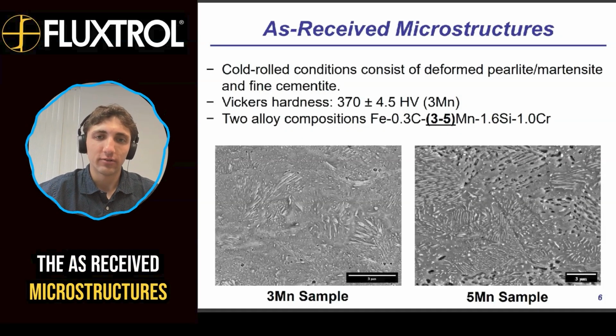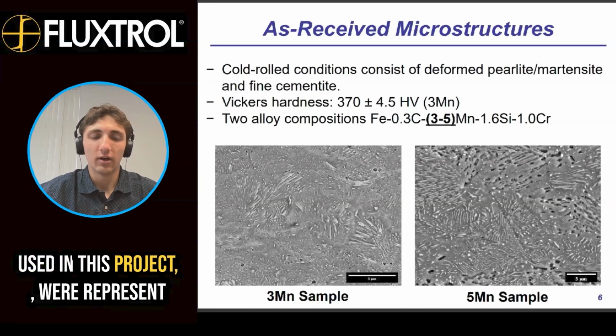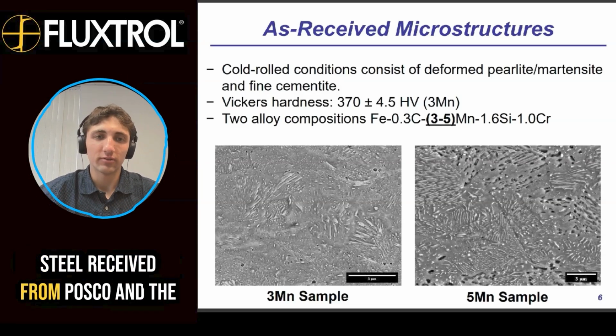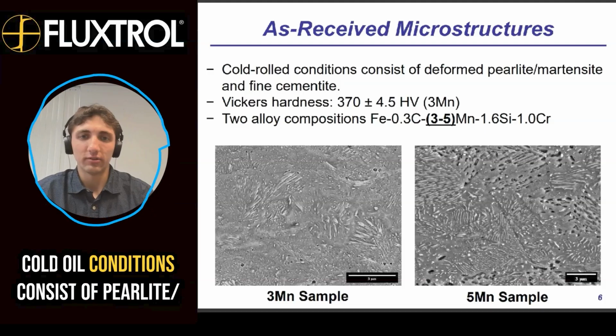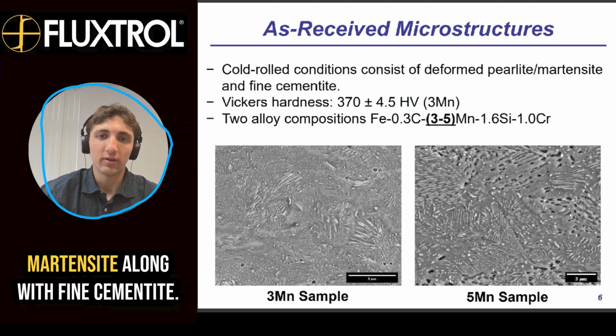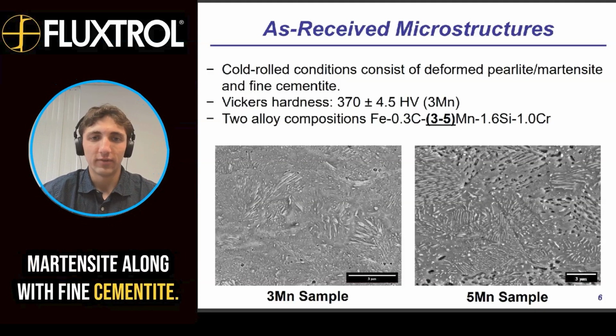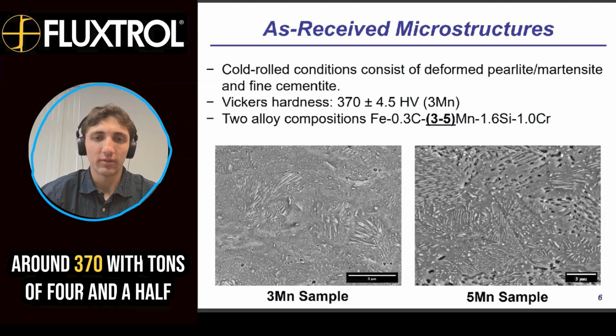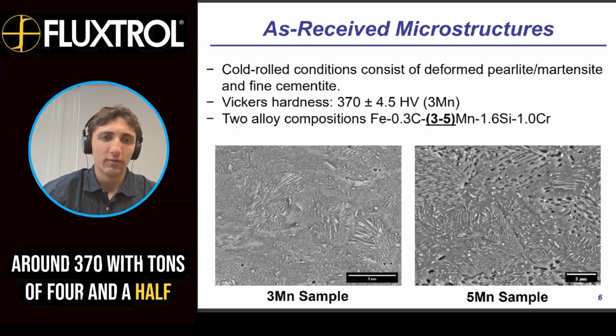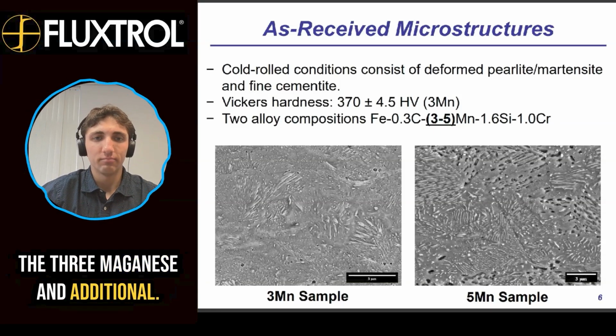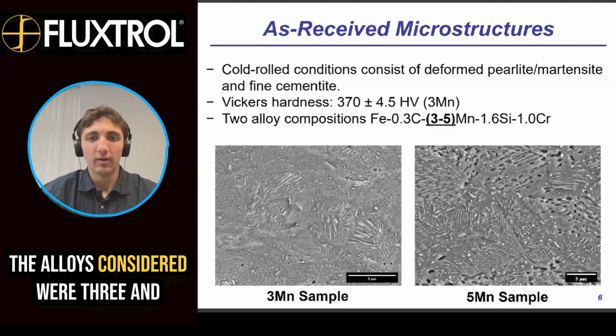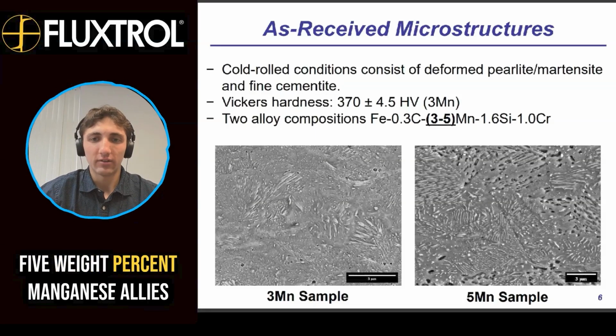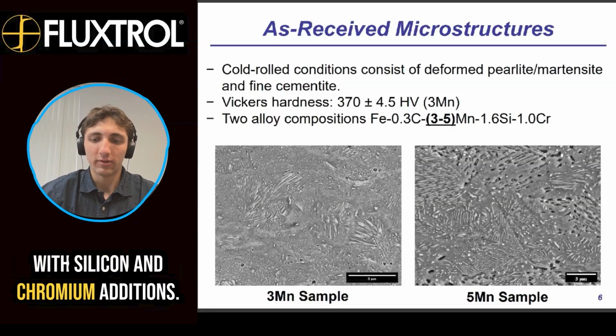The as-received microstructures used in this project represent steel received from POSCO, and the cold roll conditions consist of pearlite and martensite along with fine cementite. The Vickers hardnesses were around 370 with a tolerance of 4.5 for the 3 manganese alloy, and additionally the alloys considered were 3 and 5 weight % manganese alloys with silicon and chromium additions.